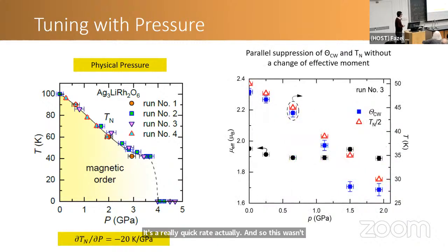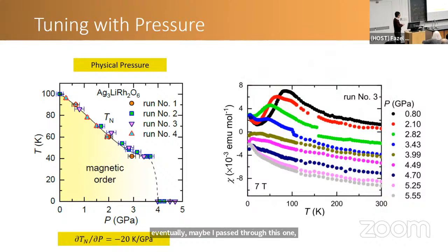And what happened was that eventually we basically lost the magnetic transition. So you see that that peak goes down at higher pressures above 4 GPa. We didn't see a continuous suppression of this peak, the antiferromagnetic transition, down to zero, but we basically lost the peak altogether. So at about 4 GPa, it's as if the system does not have that antiferromagnetic ordering anymore. So this was an interesting result. This is an unpublished result, a very recent result. We're working on a paper on this work.